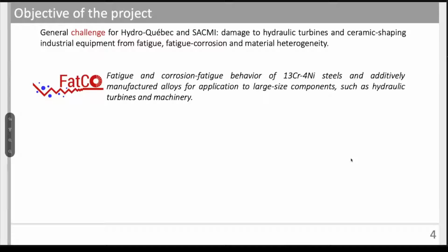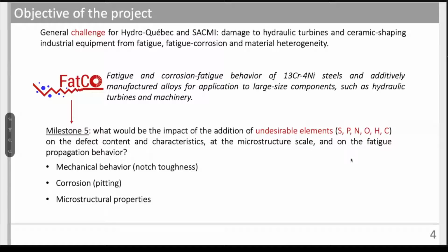This main project concerns the damage to hydraulic turbines and ceramic shaping industrial equipments from fatigue corrosion, and material heterogeneity. So my project is just one part of it, which aims at understanding and quantifying the impact of the presence of critical impurities such as oxygen, sulfur, phosphorus, nitrogen, hydrogen, and carbon on the formation and also precipitation of inclusions in this stainless steel. So more specifically, here we want to define how these inclusions impact the mechanical behavior, the corrosion, and also the microstructure properties of this stainless steel.